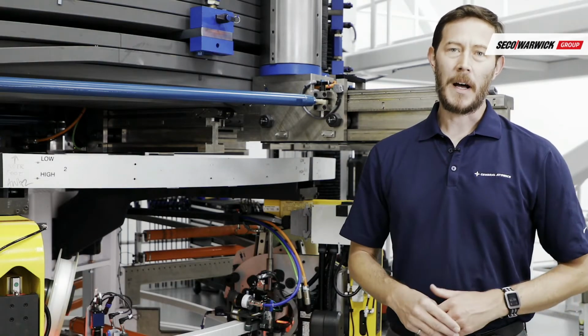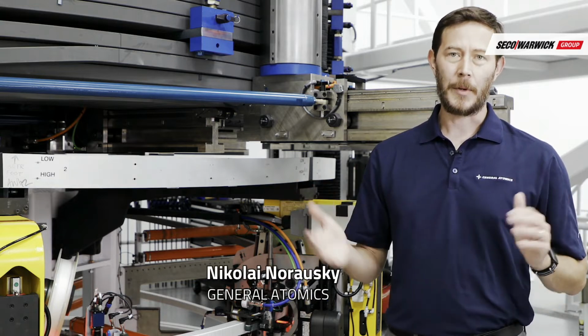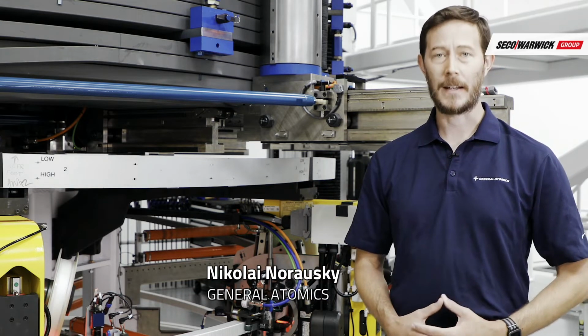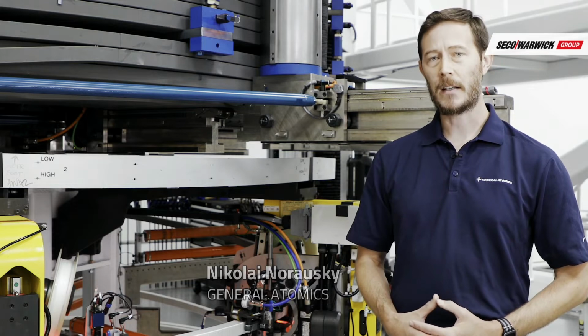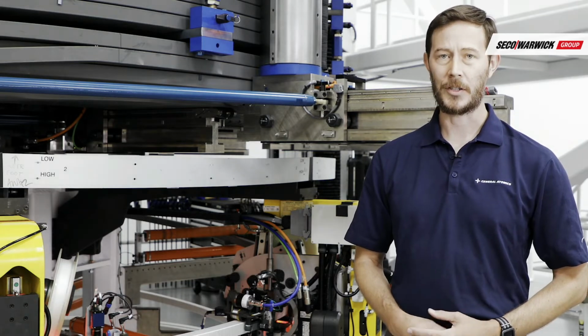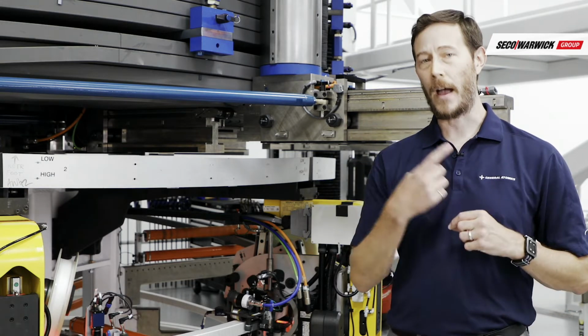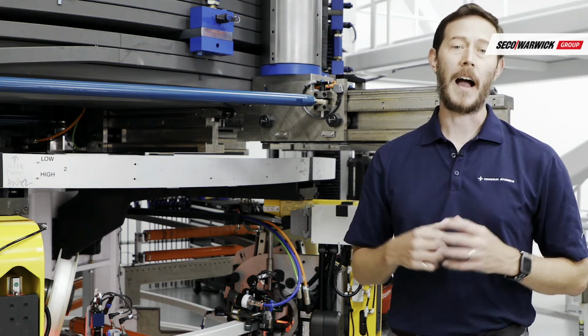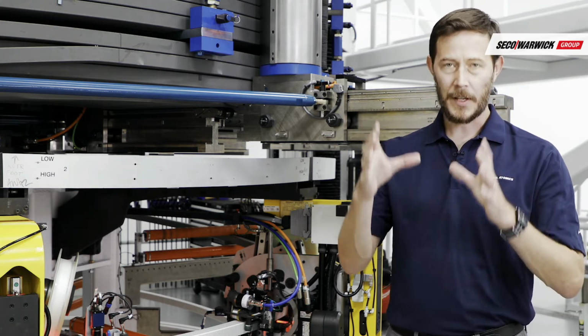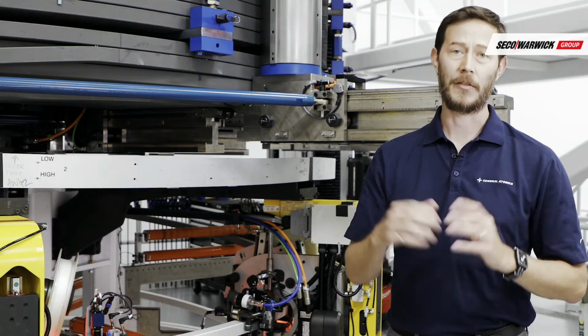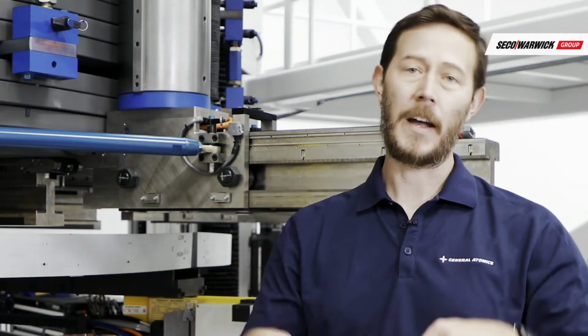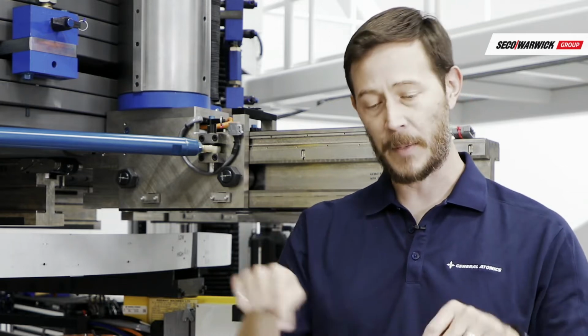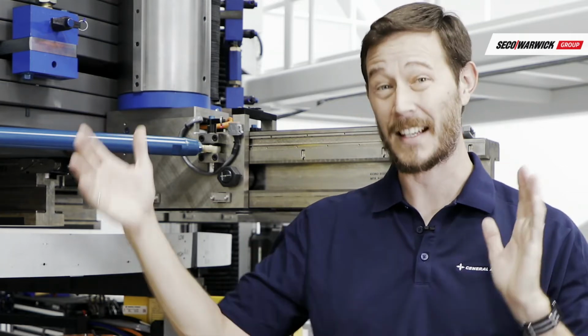Each one of our CS modules is over 4 meters in diameter, 2 meters tall, and weighs 110 tons. It's made up of 6 kilometers of superconductor in a stainless steel jacket. The conductor has to be wound in a very precise pattern of 560 turns, and those turns have to be set down in the right position within 0.5 millimeter. At the very end, the two ends of the magnet that provide all the electrical current to the magnet have to be positioned within 10 millimeters after 6 kilometers of length.